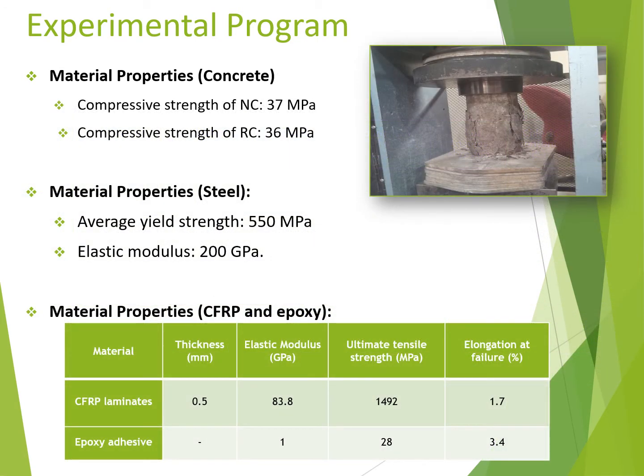Concrete cylinders were cast and cured with the beams to determine the compressive strength of concrete. The cylinders were tested after 28 days, and the average obtained compressive strength was 37 megapascal for the normal aggregate concrete mix and 36 megapascal for the recycled aggregate concrete mix.